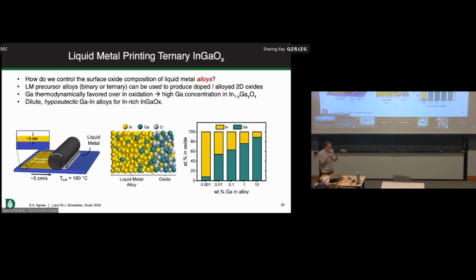Bias stress stability may not mean much to most of you, but it's the reason why we have screensavers. It's a little bit dated at this point, but if you were to look at a computer from the mid-2000s, and it goes to sleep and the screensaver bounces around to try to save your thin film transistors from bias stress. This is what also limits the lifetime of a lot of display technologies. What's happening is that the electric field can actually shift the defect distribution in your material. Oxides are vulnerable to this. Amorphous silicon, a lot of the other display materials are also vulnerable to it.